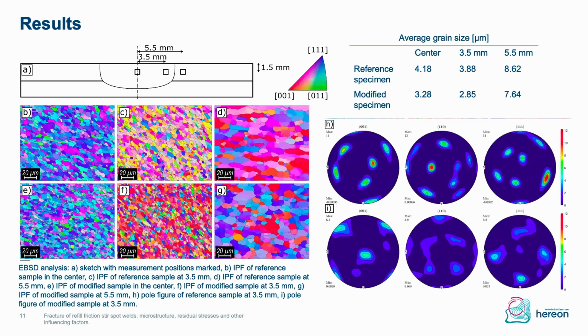So we had a closer look and did some EBSD measurements in three positions: in the center of the sample, and at 3.5 and 5.5 millimeters. Here, this is the reference specimen, and this is the modified specimen. We see that at the center and at 5.5 millimeters, we have no significant changes in the grain orientation. But at 3.5 millimeters, we significantly changed the orientation of the grains.